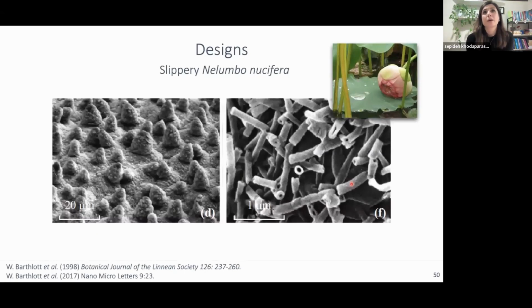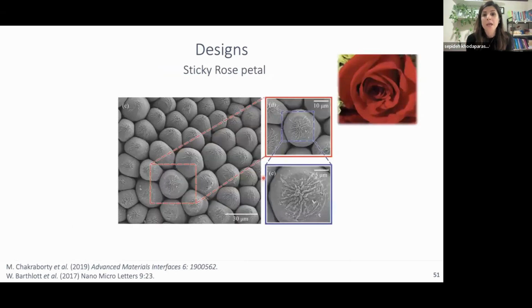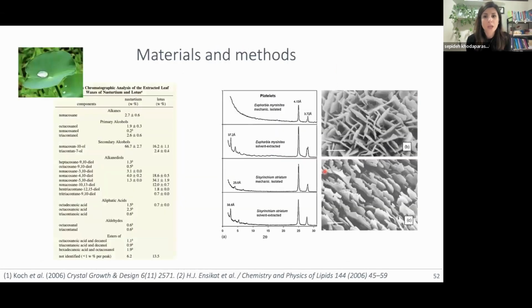So where does this wetting management behavior come from? It comes from this waxy layer on top of the surface. If you want something that is slippery, you typically, in the plants, in the larger scale designs, have this microscale structure, and on top of it, you have a nanoscale structure. For the cases where you have a sticky wetting behavior, still superhydrophobic but sticky, you have these larger structures, and the smaller structures are only at the tip of these bumps. We know, at least in terms of plants, that these structures are crystals of waxes.